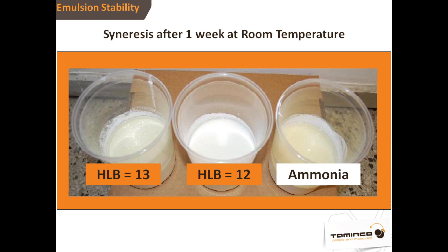The thing to bear in mind is that these alkanolamines do not imply surfactant-like behavior. Ammonia and monoethanolamine would have an HLB of 20. Fatty amines would have HLBs of about 4. Functional alkanolamines have HLB in the 9 to 15 range. But certainly don't conflate those HLBs with the HLB values that you would calculate for a surfactant.